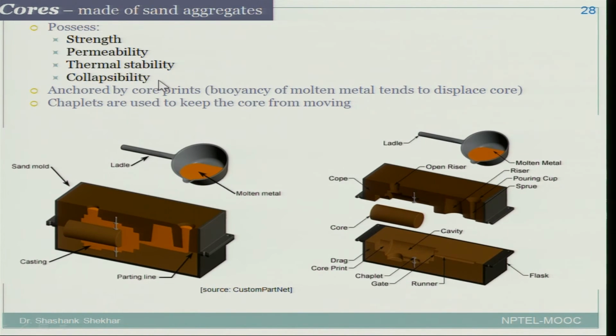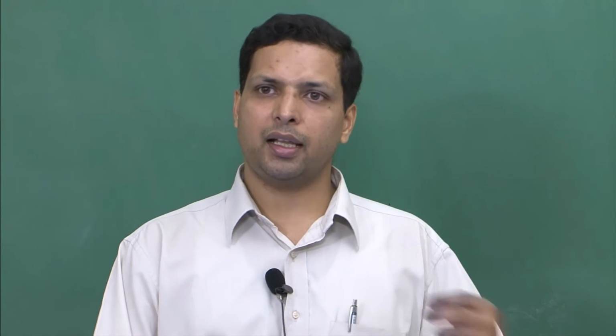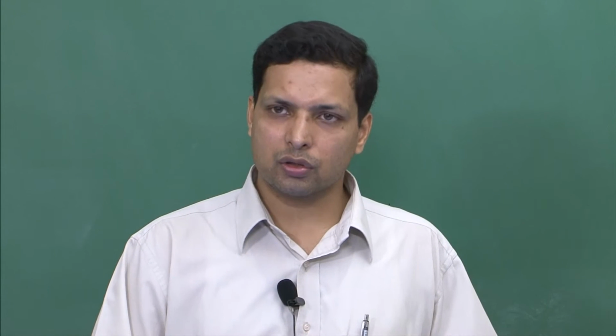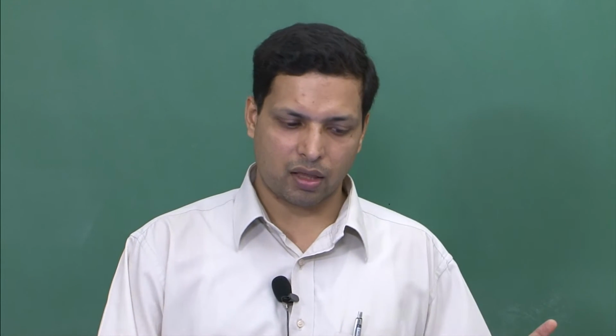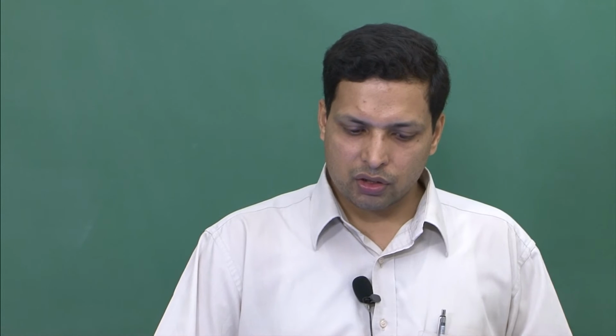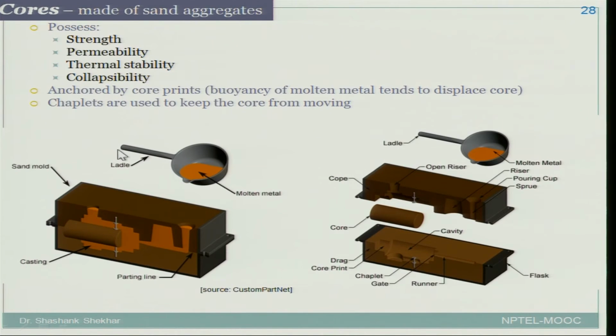And finally collapsibility. So it may look like collapsibility is the inverse of strength, but it is not really. Collapsibility you need because at the end, when you have made the component using casting, you want to break the sand and reuse it. So it should also have collapsibility along with the strength. These cores, like I said, can be anchored by core prints or chaplets to ensure that the buoyancy of the liquid does not displace it from its place.